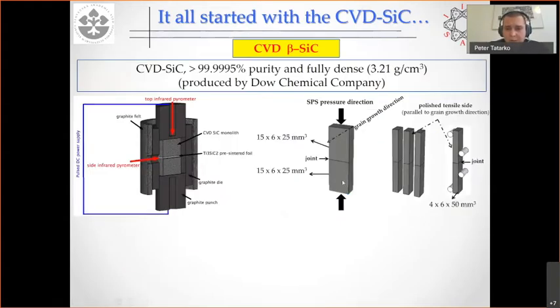So basically here you can see what we had. We've got pure CVD silicon carbide material. We've got 2 blocks, and it was quite simple. We put 1 block on another. We put in the graphite dies, and then we put it in the SPS, and we applied temperature and a little bit of pressure, and we got a joint.